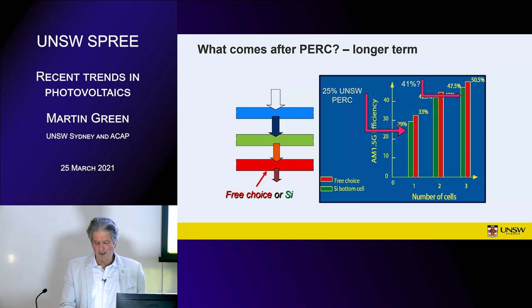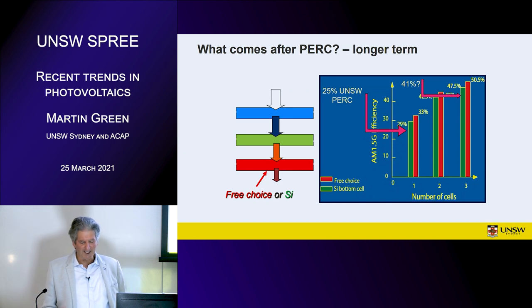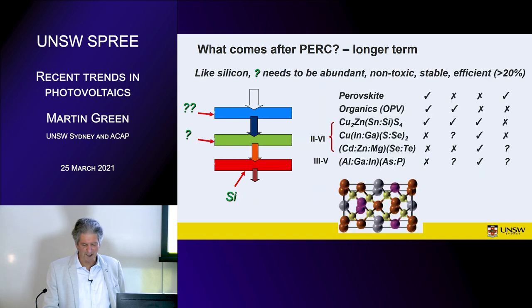And the red just shows what you'd get if you did that without silicon, had your ideal materials. So silicon's very close to the optimum, even better for a two and three cell stack than for a single cell. But the big issue is, what material do you stack onto silicon? Ideally, you need a material that has all silicon's attributes: abundant, non-toxic, stable, and efficient. And by efficient, it has to be at least over 20% efficient.